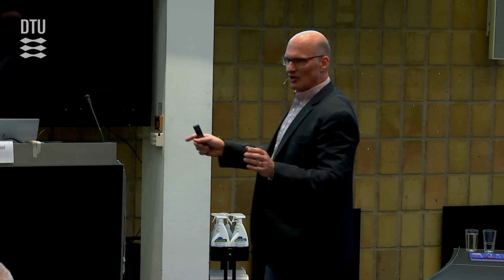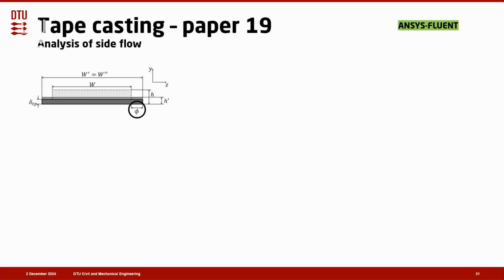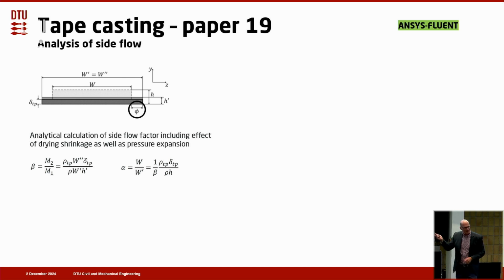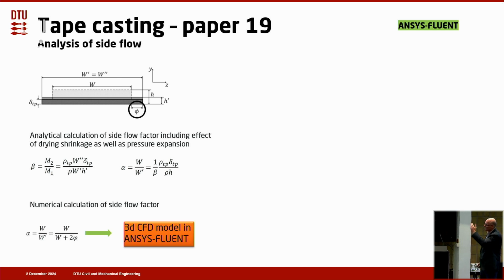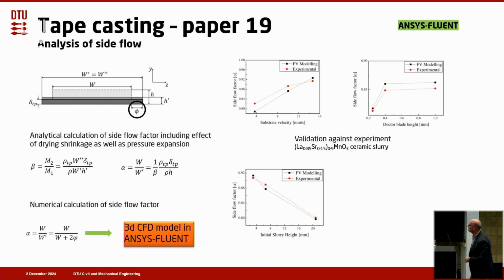We also looked at the side flow. A lot of people in literature talk about the side flow. So when you have it flowing out of the tape caster, it flows a little to the sides. And then some formulas were given in literature, but they were never derived. So we thought, okay, well, people were using these, but never told why. So we just made a small, you could say, analysis as to why it actually looked like this. And then we used a 3D CFD model in ANSYS Fluent to actually simulate the side flow. We compared against experiments for the side flow as a function of substrate velocity, doctor blade height, and initial slurry height. And we found very nice agreement.